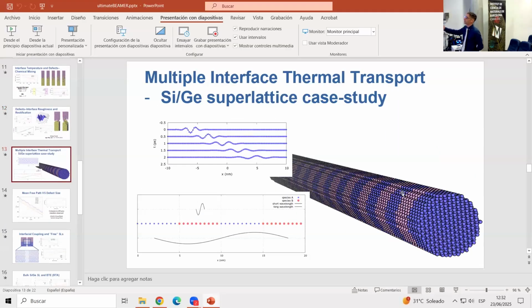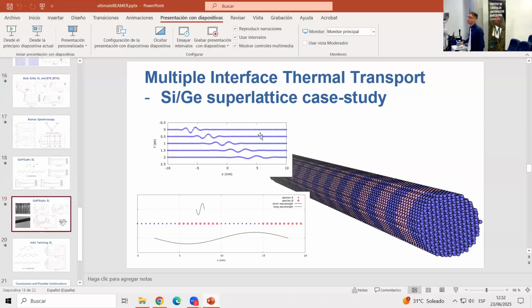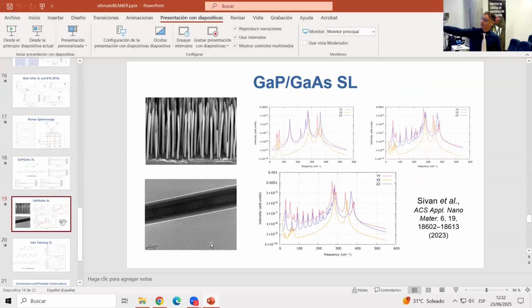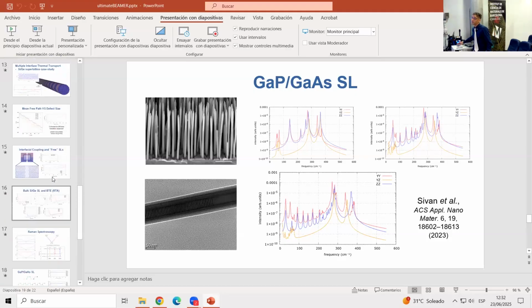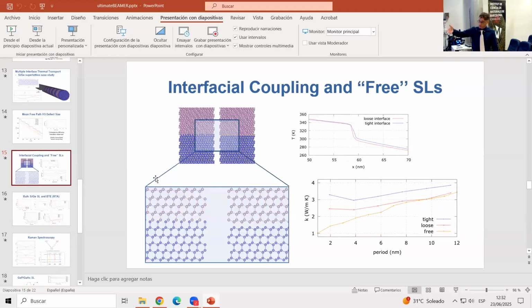unfortunately, the largest system that we can simulate is about 100 nanometers in length, and this is 8, 10 nanometers in cross section, whereas as you can see from this picture, here they have 100 nanometers in diameter. So we are completely at another scale. This influences the simulation in a very large number of ways. So I would say that this is fascinating, because in the experiments, coherence is observed. There are very, very famous papers where this transition has been observed in practice, not only in the simulation. So we are super happy with that.